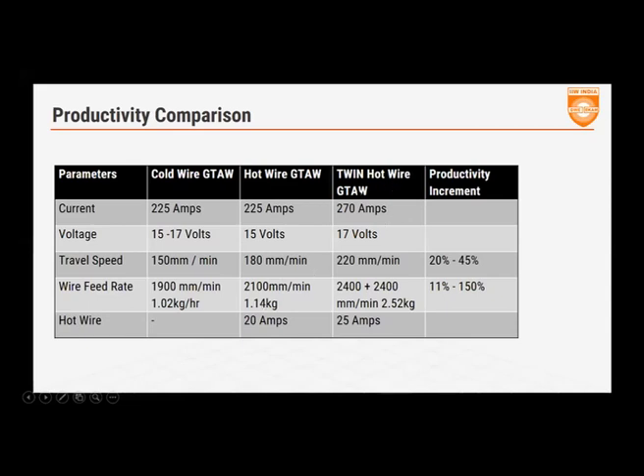Now, what happens when we did the twin hot wire? You look at the change in current. There's hardly a change, about 20% in current. Voltage, more or less about same. You have increased your weld speeds to about 220 millimeters per minute on the job, which is a 45% increase in your productivity, the job movement. And look at the deposition rate. It's moving right from 2.1 per single wire to twin wire hot wire, moving at about 2.5 kgs per hour, making it upward of about 150% than what you were doing at the one cold wire feeder. The heat input, if you can calculate over the speed, would be equivalent or less. There would not be more heat input.